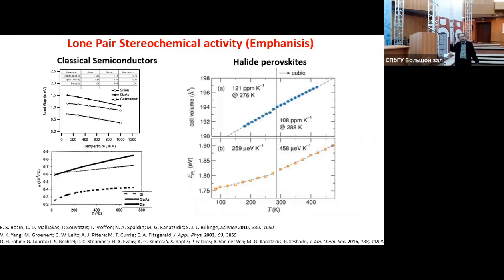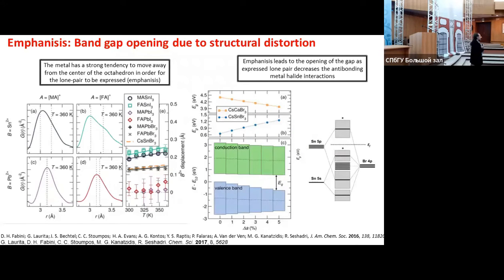And this also has a consequence on the properties, because if we try to compare with classical semiconductors in terms of what effect the temperature has on the optical bandgap and also the thermal coefficient, because we want to know what happens to the lattice. We see that we have a massive thermal expansion coefficient, volumetric coefficient, much larger than what we expect for the classical semiconductors. And we also have an increase in the bandgap as we increase the temperature, contrary to what we see for normal semiconductors. And we try to analyze this property. It's a consequence of this dynamic disorder that I described just before.